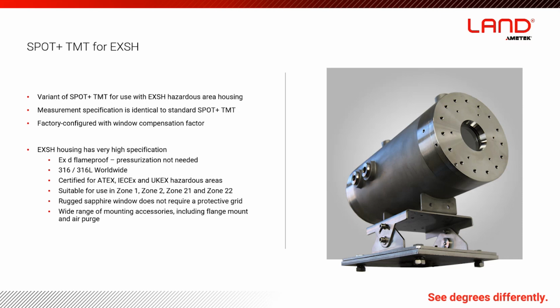Here's a picture of our EXSH enclosure. That's a flame-proof housing for use in hazardous areas. So it's EXD protection concept in the language of hazardous area certifications. We mount the SPOT TMT for the EXSH inside this housing. And that means it can be used in Zone 1, Zone 2, or Zone 21 and 22 if it's a dust application. It comes factory configured, so there's no need to adjust a window compensation factor if you put it in there.